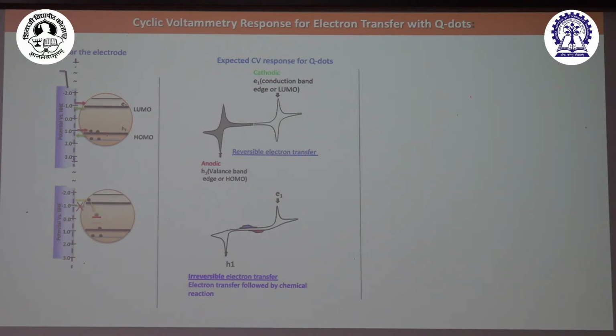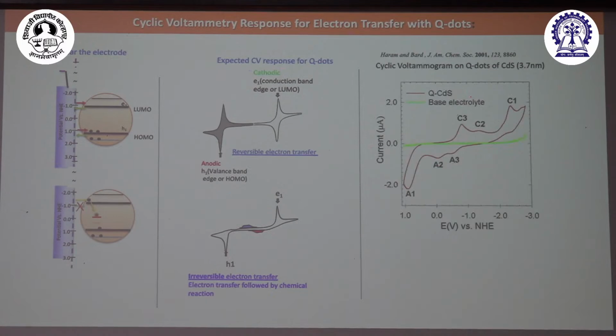Okay, so if my electron transfer is reversible, I will get this kind of response. If it is irreversible, I will get this kind of response. With this hypothesis, we did the experiment long back, 22 years back. And we found that the way we thought of, we got the cyclic voltammogram. This is for quantum dots of cadmium sulfide. Here this green line is a baseline. If there are no cadmium sulfide quantum dots, you get this baseline. And once you add cadmium sulfide quantum dots in the solution, you get this kind of response.